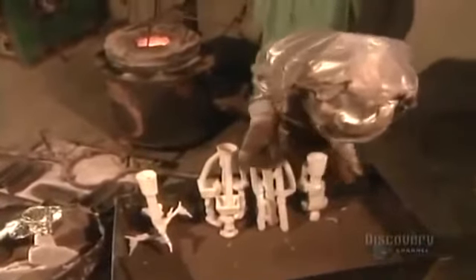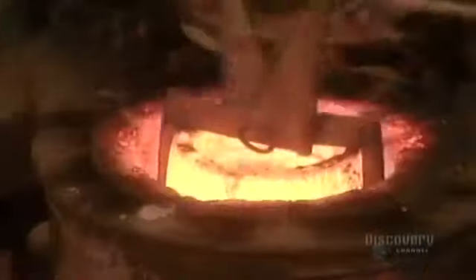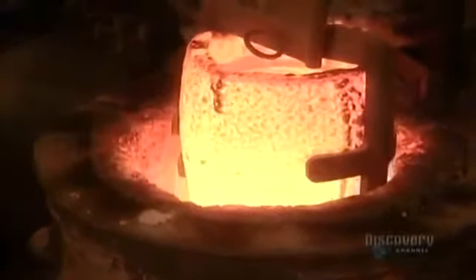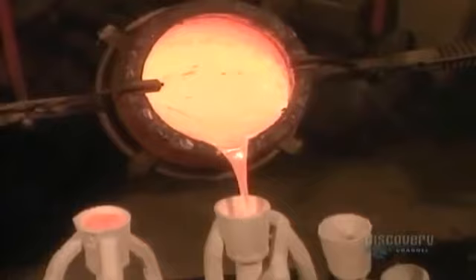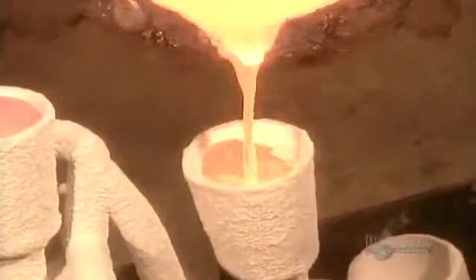That mold goes into a kiln at 850 degrees Celsius. After 2 hours, it's fired. This is the finished mold into which the bronze will be cast. At the foundry, they heat the bronze to 1,140 degrees Celsius. Then carefully pour it into the mold. The molten metal takes just a few minutes to solidify.